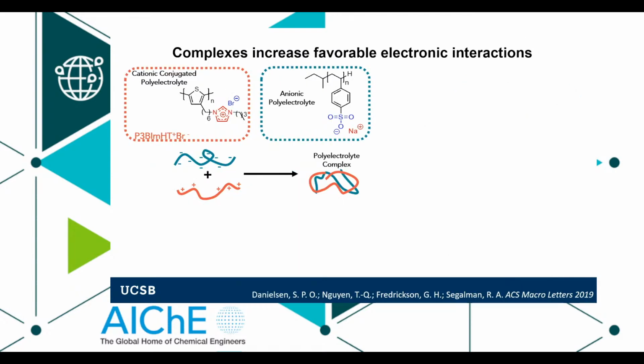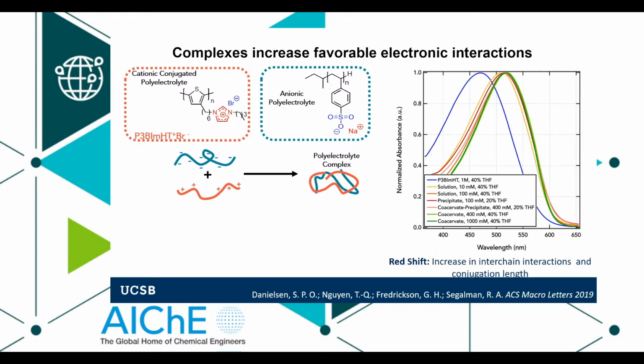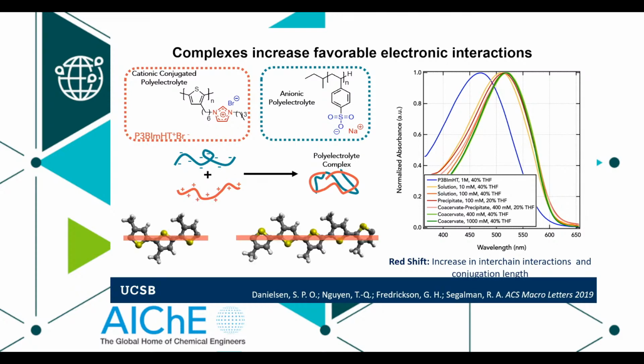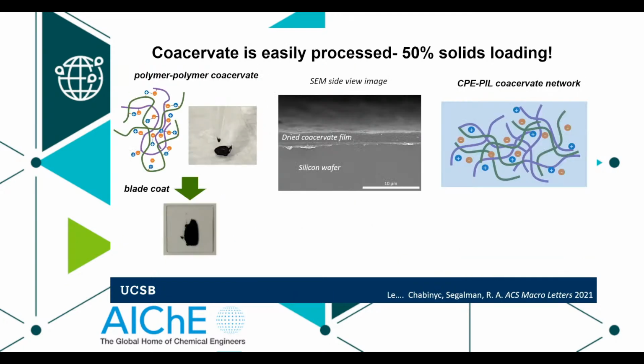The other thing that's really neat is that the biological coacervate community knew that when you coacervate two chains together, it tends to stretch out the chain in order to maximize contacts, right? When you stretch out a conjugated polymer chain, it increases the conjugation length. You get a red shift in the optical spectroscopy, which is kind of cool, because what that indicates is we're able to transport charge or delocalize charge over longer distances, right? And that may be important for the overall performance of the system. We're getting an added benefit by coacervation, even at the first glance at these systems. So what we do is we take that low viscosity coacervate that's now 50% or more solids loading. We can now blade coat it. It just happens to be the right viscosity for us to blade coat easily.